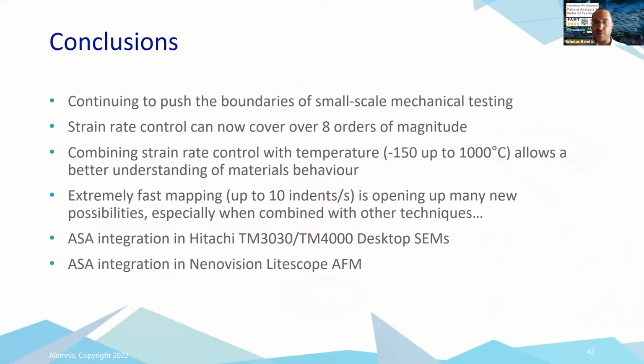So the question then is, we have the instrumentation to go very fast, but does the test at that speed really make sense? If we want purely mechanical properties, then maybe 10 indents per second is a bit too fast. But if we just want to compare a surface and map it, then it can be quite useful because we get a lot of data points very quickly.